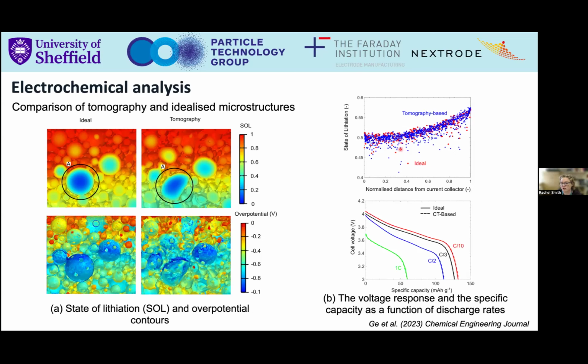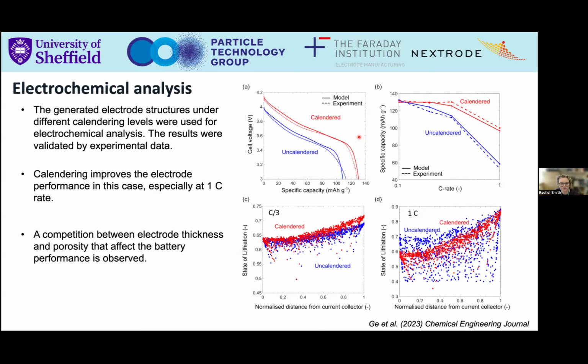So what we found was that you get, on a microstructure scale, you do get some variation between our simulations, but on average, if you're looking at the performance of the electrode, and you can see this here on the cell voltage level, we're getting almost identical results. And so that was very good. We're able to acknowledge that we're not going to capture the distribution, for example, of the state of lithiation inside the electrode, but overall we can capture the general behavior.